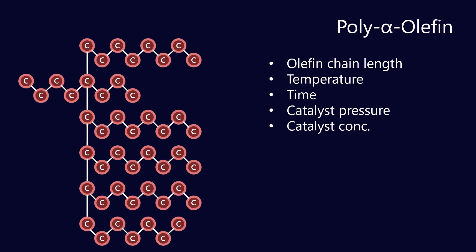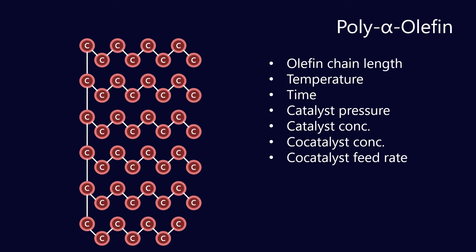The other things that you can change are catalyst pressure, catalyst concentration, and the type of catalyst. I use the example of boron trifluoride but if you want higher molecular weights than about 20 centistoke - and I should note that in the base oil market finished lubes tend to refer to viscosity at 40 degrees Celsius whereas the base oil market does it at 100 degrees Celsius - but if you go for high molecular weight base oils then you're going to need a different catalyst. There is actually another technology out there which is a metallocene catalyst which produces metallocene PAOs which have non-branched structures beneficial for the viscosity index.